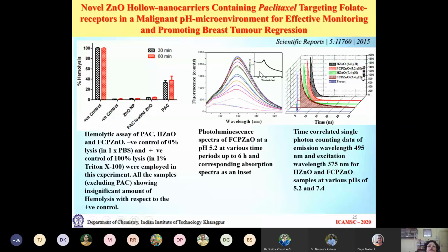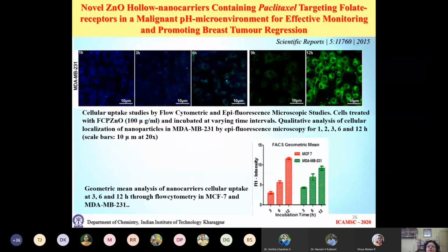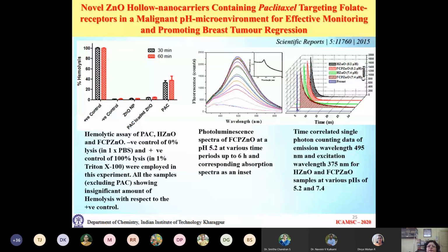So if you have such a readout, then it is obviously going to be very important even for diagnostics, because not only is it getting ruptured and getting inside the cytoplasm of the cell, and the endosomal unit of the cell, but it is also giving you a signal that it has entered, by having a very high increase, even a 10-fold increase in the photoluminescence property.